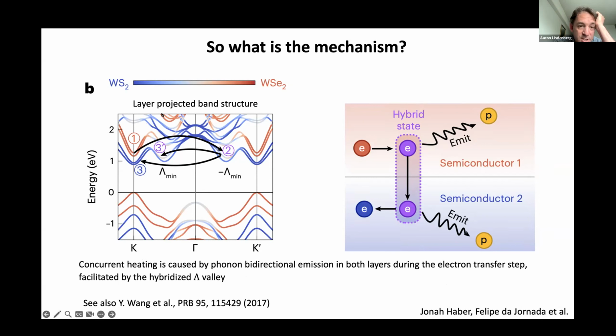So here's the cartoon picture of the band structure, the layer projected band structure. Red here corresponds to contributions from the WSe2, blue from the WS2. So in the initial step one excitation process, we're populating the K valley of the WSe2, this region right around here. Okay, and there's essentially negligible hybridization with the K valley of the WS2. So this is again saying that there's no mechanism for direct coupling between these two structures.